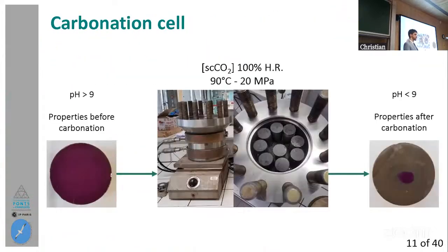So there, it was the carbonation cell. I had put some centimeters of water in the bottom before putting my samples. And there I put, if I remember well, 18 samples or specimens of cement. And finally, I closed the cell and I started injecting the CO2. This was done until reaching the pressure that was in the tank of CO2, which was around 5 megapascals or so. And then I started increasing the temperature. With the temperature, also the pressure increased until reaching these conditions. So I reached 90 degrees centigrade and 20 megapascals. And I kept that constant throughout the whole exposure time, which was 60 or 120 days.